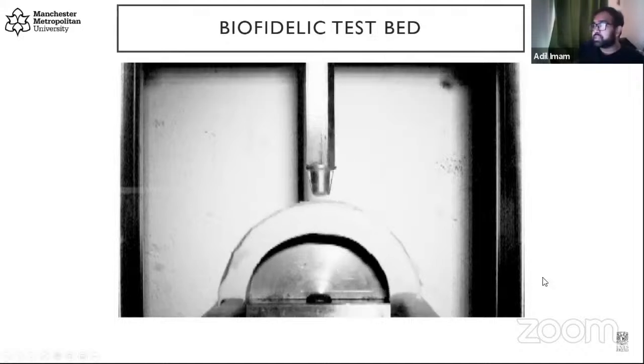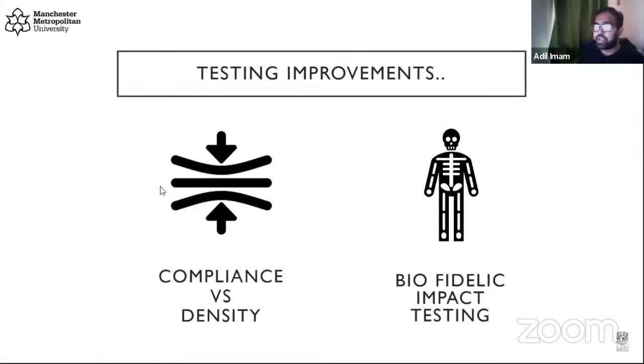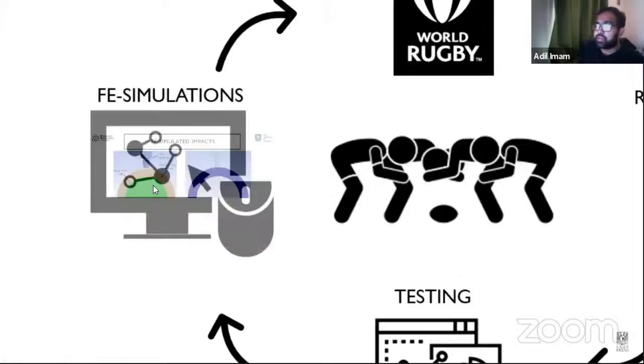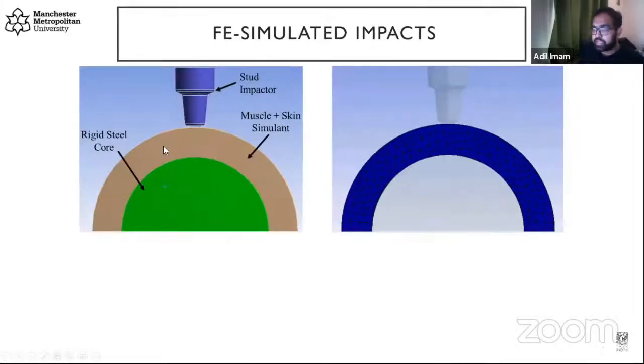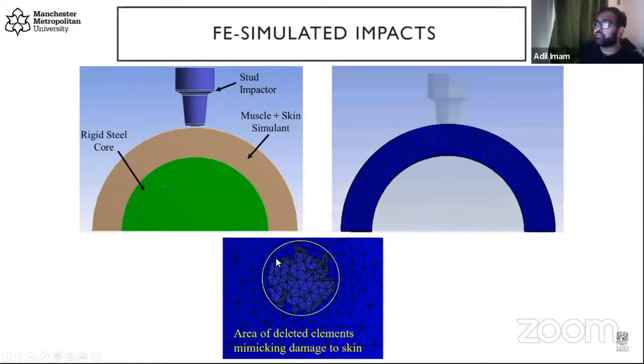Now, using this data, we were able to carry out some FE simulations. So the simulations we did was based on the muscle and skin simulant, which Angus developed. We did some material testing, built our different material model, and then carried out some testing with the stud coming down to see what would happen, and introduced element deletion criteria to mimic the injury that would occur on the human skin tissue. So again, FE simulations are an easier way of simulating such injuries, because we'd never get ethics for testing out on humans and impacting them with stuff to see how their skin reacts.